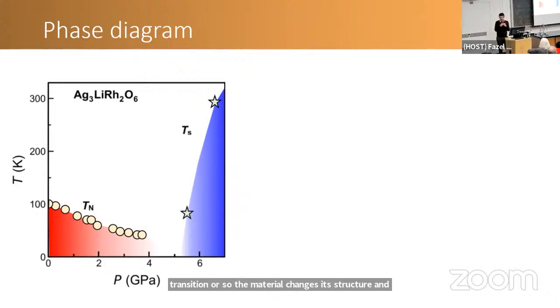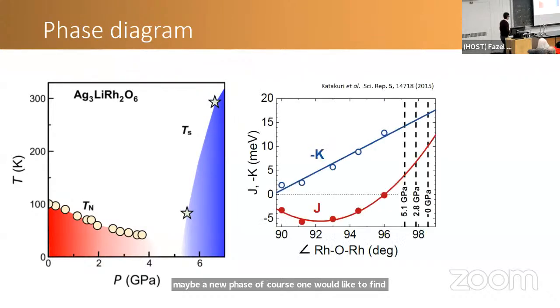So the material changes its structure and the physics is basically gone. But here I present this material as a window of opportunity, in some sense, to look at a region where you suppress magnetic transition before you get a structural transition. We have not yet done lower temperature measurements, but of course there could be some interesting possibility at these low temperatures, maybe a new phase. Of course, one would like to find superconductivity in these honeycomb materials, but anyways, we'll see how that goes.